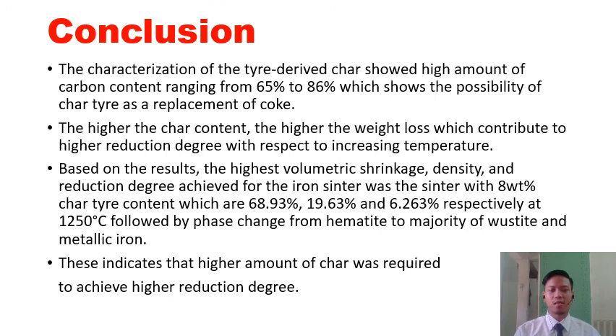Third, based on the results, the highest volumetric shrinkage, density and reduction degree achieved for the iron sinter was the sinter with 8% composition of char tire content, which are 68.93% of shrinkage, 19.63 for the density, and 6.263% of reduction degree respectively at 1250 degrees Celsius, followed by the phase change from hematite to majority of wustite and metallic iron. This indicates that a higher amount of char was required to achieve higher reduction degree.